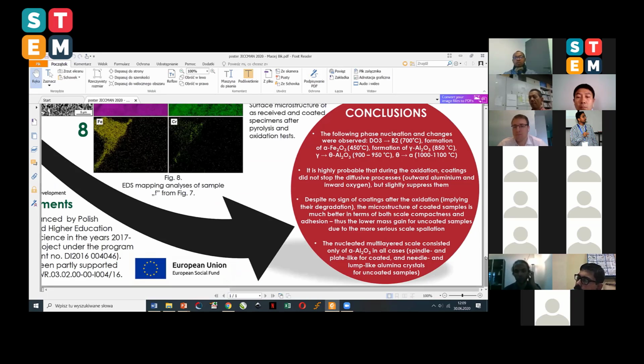So to conclude, plenty of phase transitions could be observed during in situ XRD investigations for this novel iron aluminide alloy. So not only alpha alumina changes, but also a phase transition of the material itself. And it is highly probable that during the oxidation, coatings did not stop the diffusive processes fully, but slightly suppressed them. And the multi-layered scale was nucleated after the oxidation, which consists of needle-like and lump-like alpha alumina crystals. And also the most interesting part, that the morphology of the samples changed a lot because there was nearly no spallation observed.